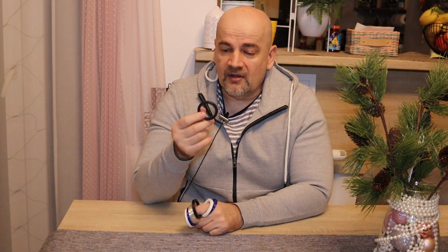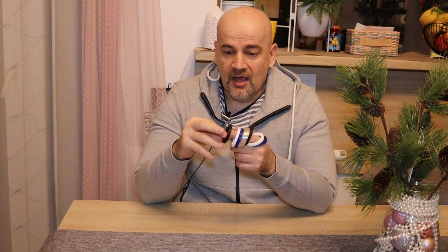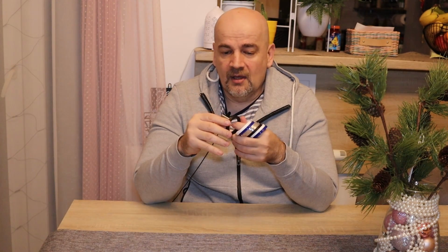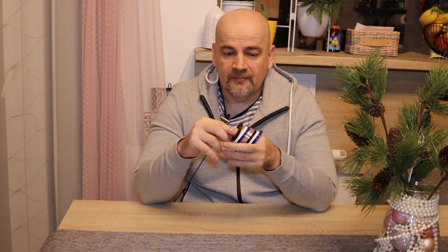About these filaments, the medium and hard are more or less similar to each other. The semi-soft is definitely more elastic compared to these three. Now, a very pleasant surprise was this carbon fiber hard version, because very often I can see that adding carbon fibers to some material makes it weaker. Here it is not the case. Actually it was stronger in most of the tests. Of course we lose some elasticity, but for example very impressive was the layer adhesion test, where it was actually the strongest, or maybe the temperature test, 150 degrees Celsius, so that was also very impressive.